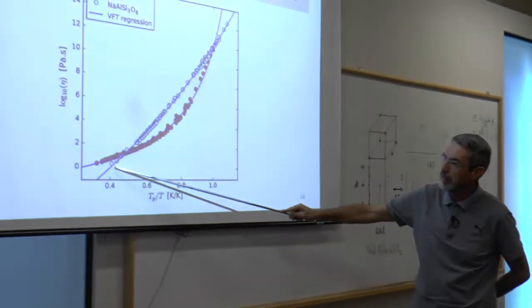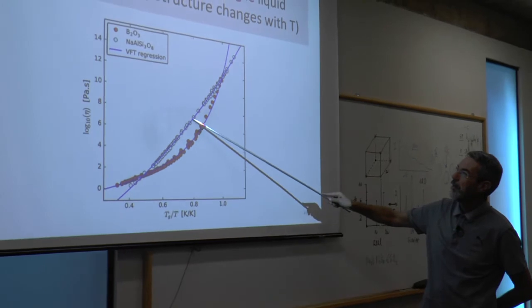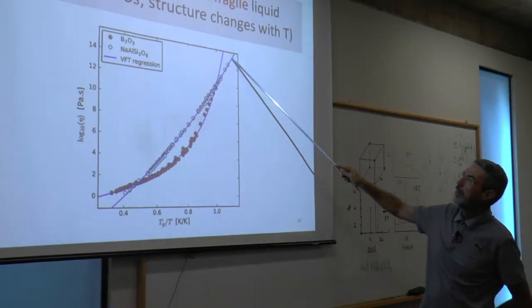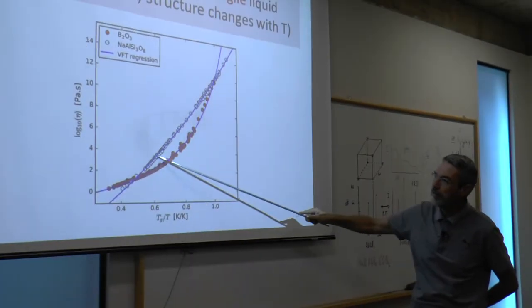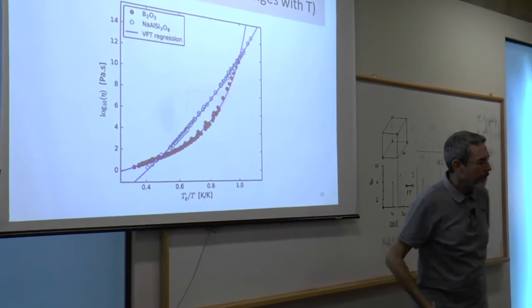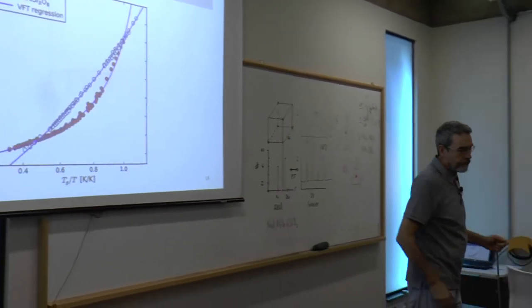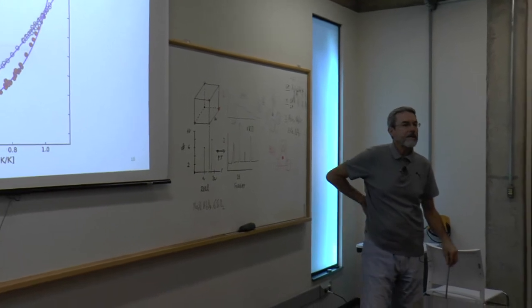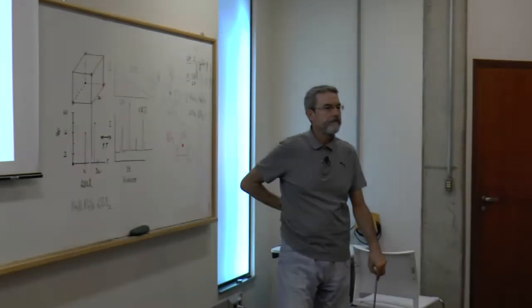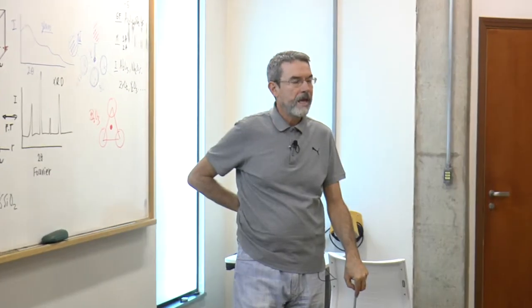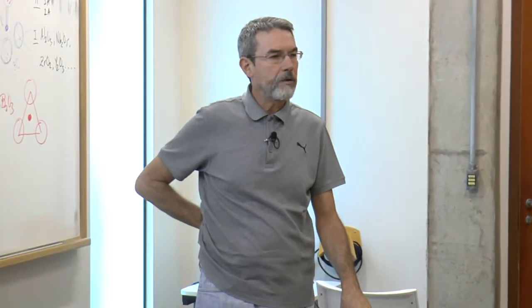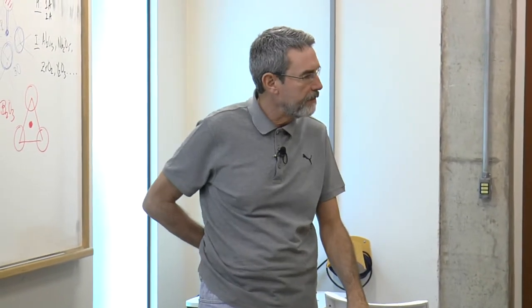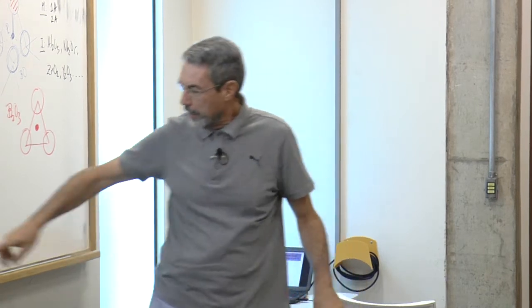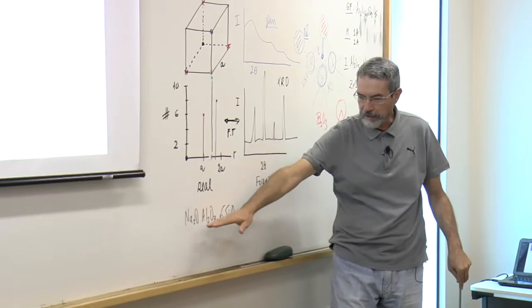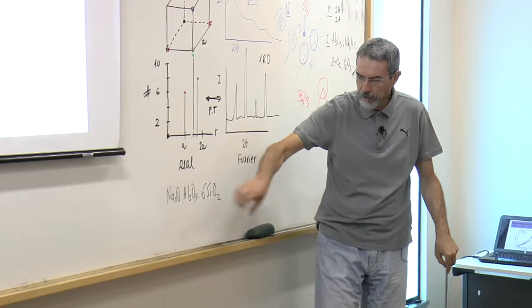and this is the viscosity of this glass, very strong and almost Arrhenian. See, this viscosity here is almost Arrhenian because it no longer has non-bridging oxygens. It's not perfectly Arrhenian. Why it's not perfectly Arrhenian? Looking at this, it should be perfectly Arrhenian. It has 0 non-bridging oxygens.